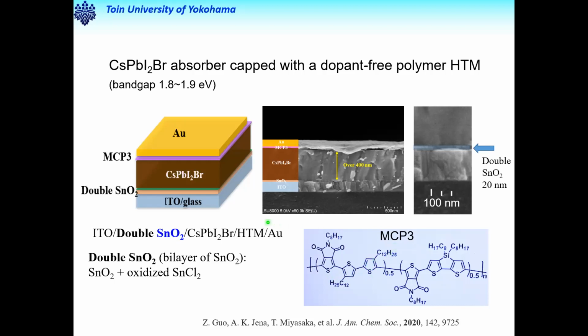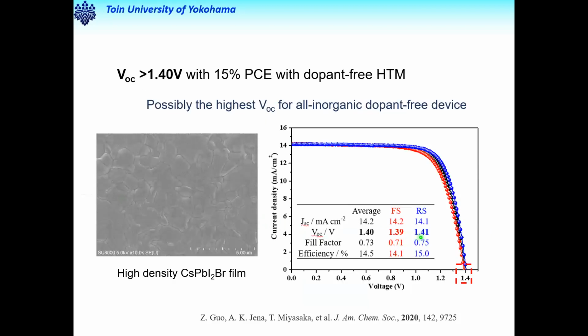By making this solar cell, by coating perovskite on the cheap tin oxide layer, we could achieve 1.4 volt output. This is a very recent result we published last year. This is very impressive performance of perovskite in terms of the very, very high output voltage from a perovskite solar cell, 1.4. The band gap of this cell was 1.9, so there was still a loss of 0.5 volt. But I think this 1.4 or 1.42 volt is the highest voltage obtainable from a single perovskite solar cell.